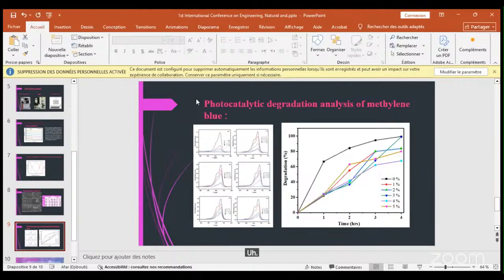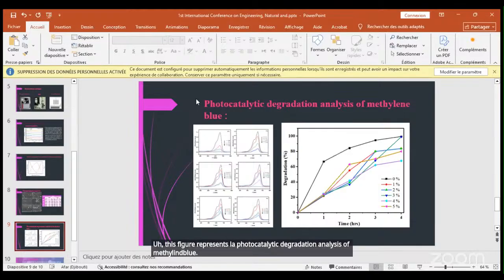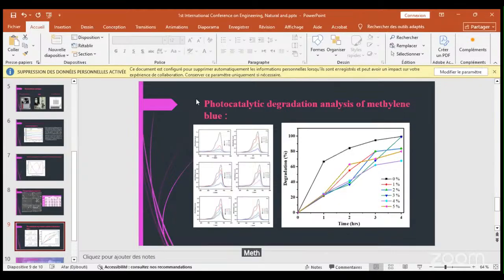This figure represents the photocatalytic degradation analysis of methylene blue. The photocatalytic activity of undoped and aluminum-doped zinc oxide thin films was assessed through sunlight-induced degradation of methylene blue. The degradation rate and absorbance change at 664 nanometers are shown, and the figure shows that both undoped and aluminum-doped thin films efficiently degrade methylene blue, confirming their photocatalytic efficiency as shown in that figure.